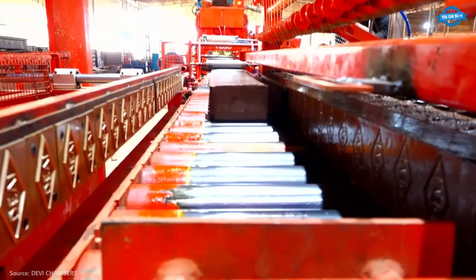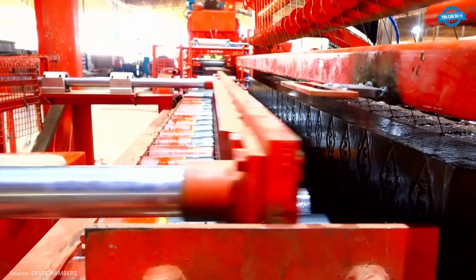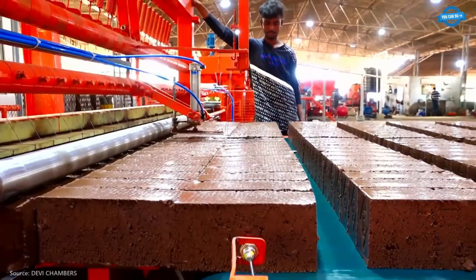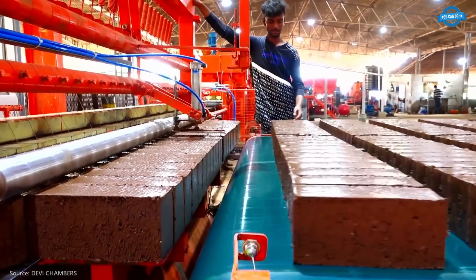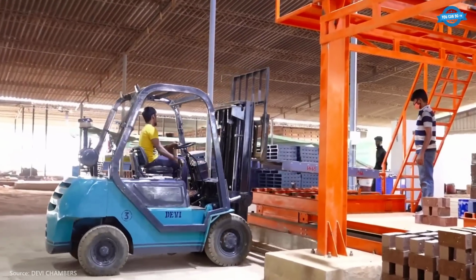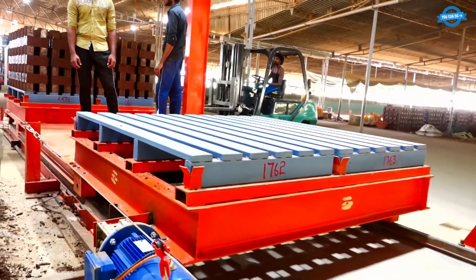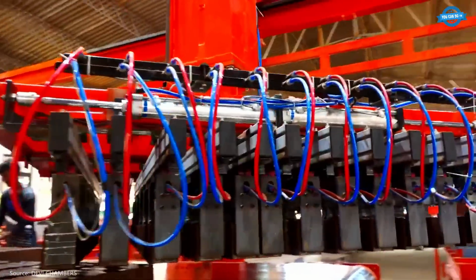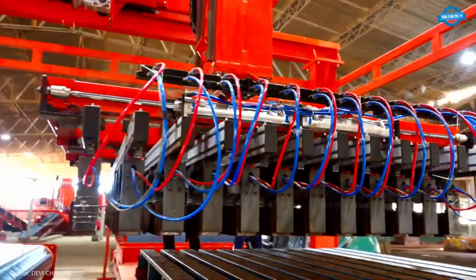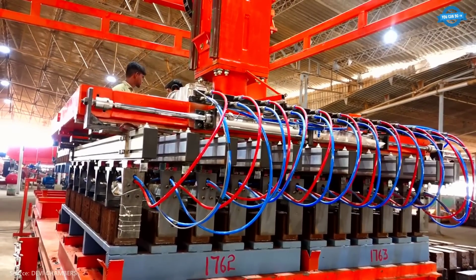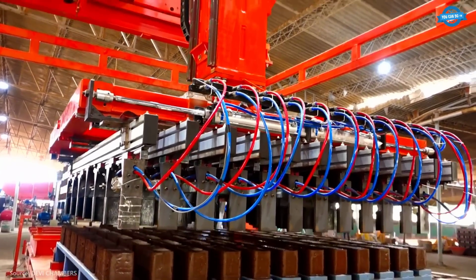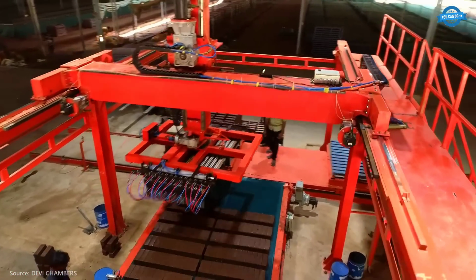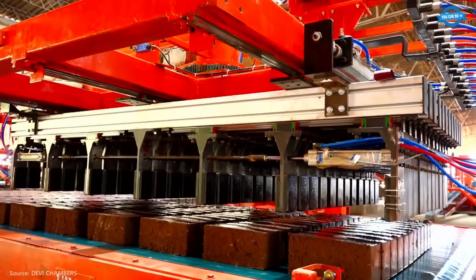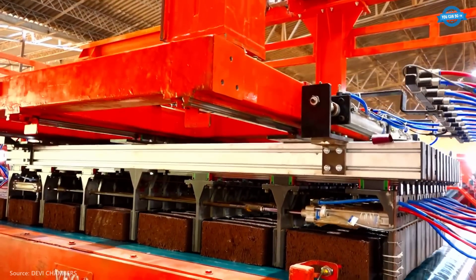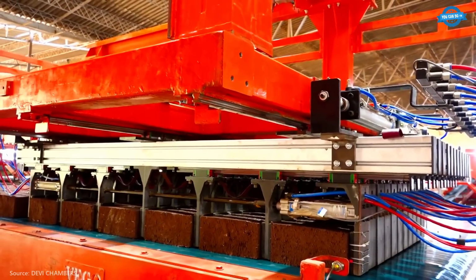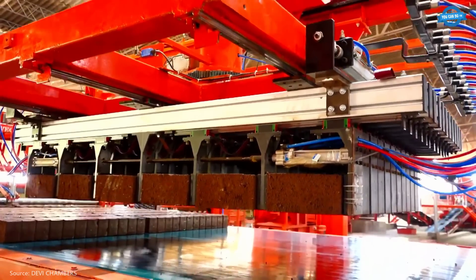Water is then added to the mixture, which undergoes a 5-stage mixing process in a final mixer to achieve perfect clay consistency. The unique 5-stage mixing system was developed to enhance precision in the blend. The resulting clay is passed through a vacuum extruder that de-airs the material, increasing its density and wet strength. The extruded clay emerges in long columns, which are cut into individual bricks using advanced hydraulic cutting machines equipped with precision sensors for accuracy.